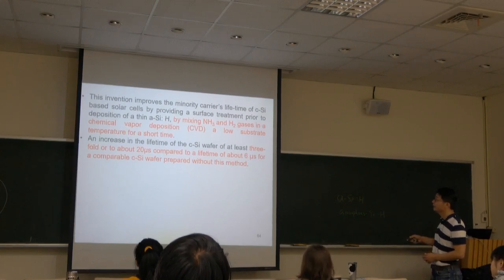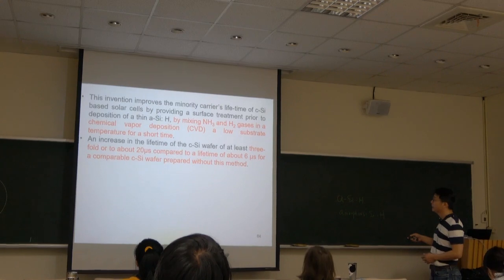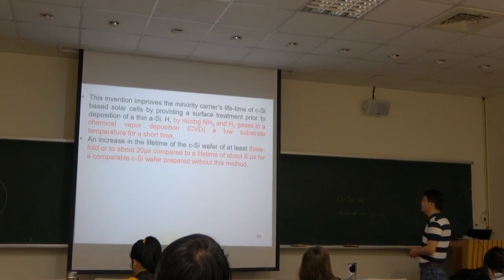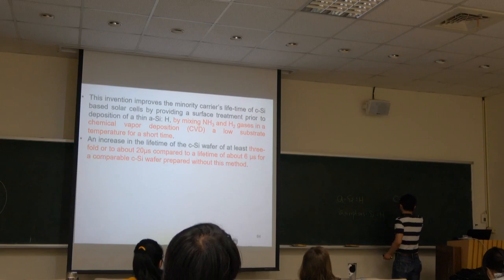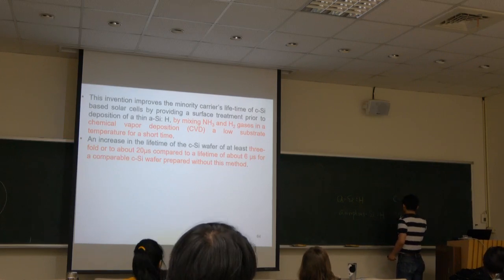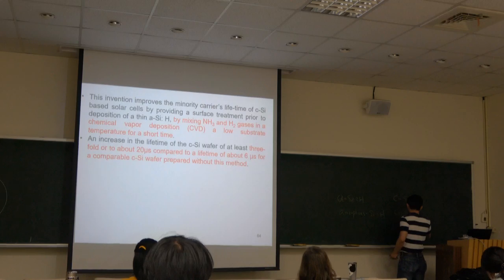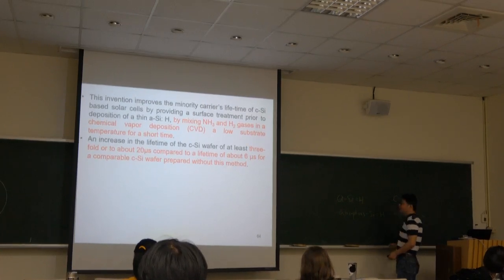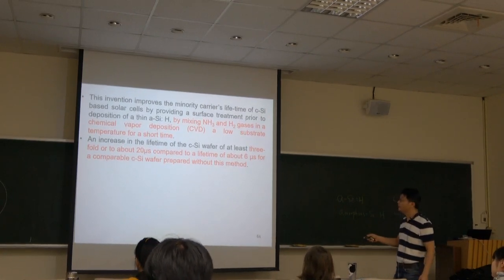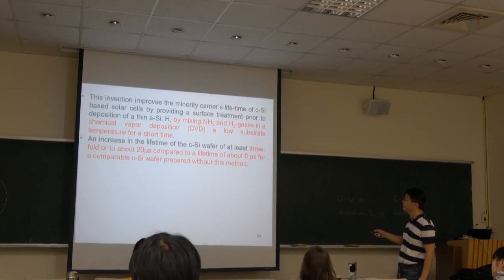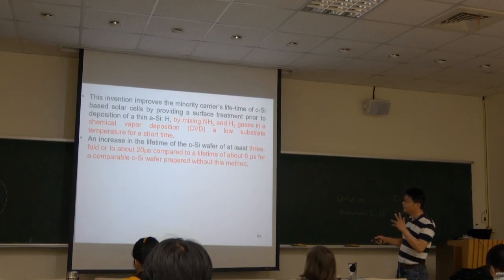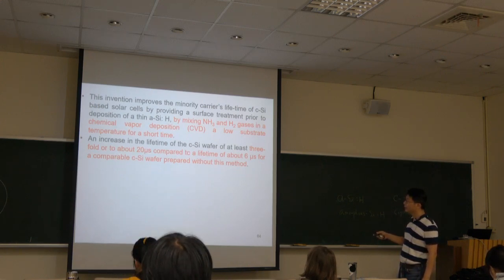This is a comparison: an increase in the lifetime of the crystalline silicon wafer of at least threefold, or to about 20 microseconds compared to a lifetime of 6 microseconds for a comparable crystalline wafer prepared without this method.